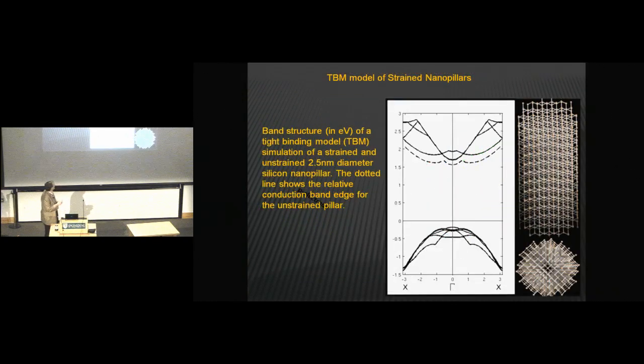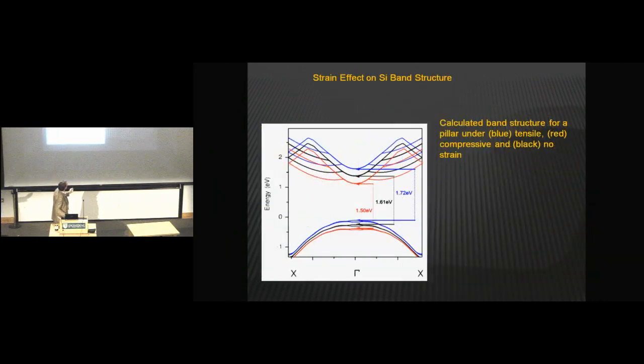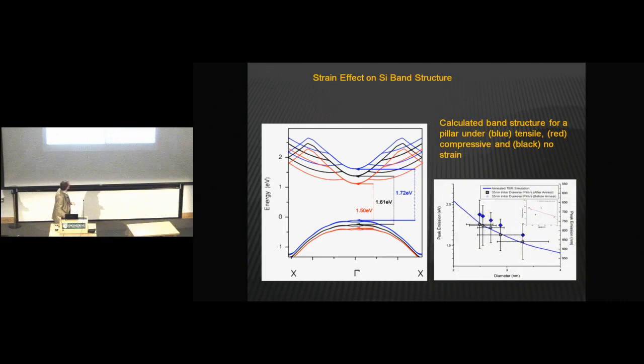You've actually changed the band structure so it becomes direct because you've made a very small whisker and you've put it under tremendous tensile strain. Okay? You can calculate the effects by using tight binding models and so on. So this is very interesting because now you've made a material that's chemically silicon, but geometrically you've changed things. You've introduced basically a change. And you can measure this.